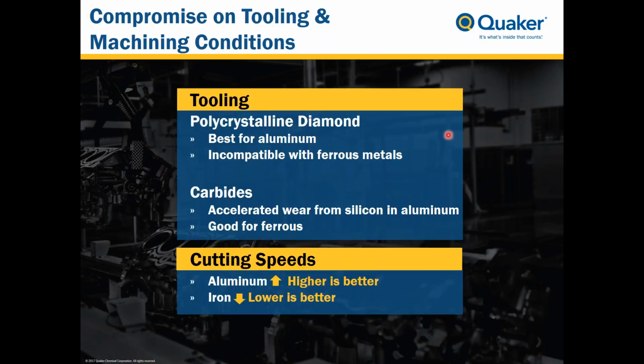A second example is cutting speeds. Quite often with aluminum, like I mentioned, you're able to run at higher cutting speeds, and with iron, you need to go at lower cutting speeds. So again, you're typically trying to reach a middle value where you can sustain acceptable quality for the aluminum and the iron.